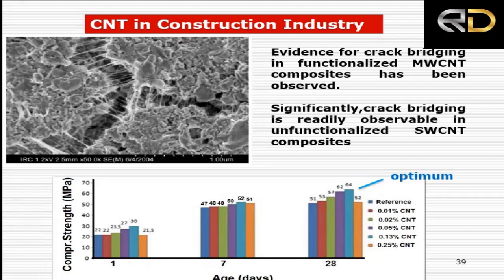Further, if you just simply add 0.13% of carbon nanotube in the concrete, the compressive strength becomes much higher as compared to other. So the carbon nanotube increases the compressive strength. It increases the durability also because the pore size is decreased.